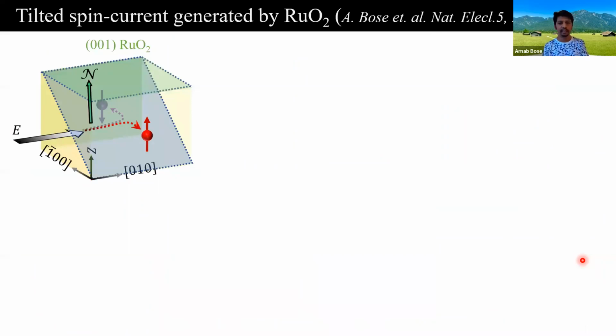So let's consider the single crystal ruthenium dioxide as shown here. So this is the 001 direction, and this is the 001 plane. The theory predicts that when we run in-plane current or in-plane field along this 0, 1, 0 axis, then it creates transverse spin current along minus 1, 0, 0 axis, perpendicular to this. And spins are parallel to this Néel's vector.